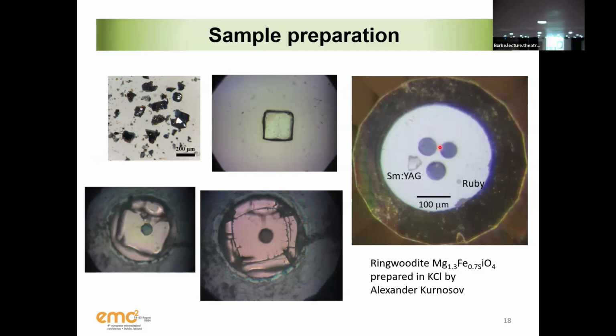Because what you want to do is to hit the whole crystal. You don't want to hit just a part of it, because then you will have cracks developing, and then you lose your nice surface, and you have to start again practically. You cannot measure acoustic velocity if it is cracked. So that's the way we prepare it. And usually we try to put at least 3 crystals in there, so that if one of them is burnt, and it happens more often than you think, then we have another one to measure.